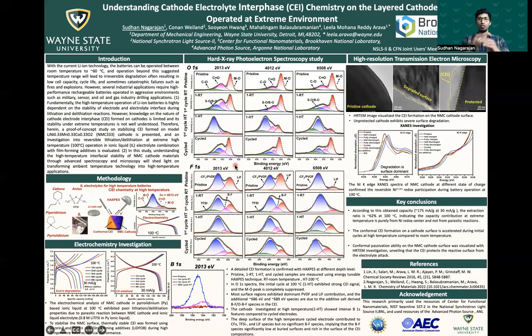So after that, we wanted to understand the surface of the NMC using hard X-ray photoelectron spectroscopy, using different photon energies. We use different photon energies to understand the cathode interface at different depth levels. The take-home message of the oxygen 1s spectra is that at high temperature during initial cycles, the cathode interface formation was accelerated. And from the fluorine 1s spectra, we clearly see that the boron-based surface species are emerging in the surface regions compared to deeper surfaces. So we supported that with the boron 1s spectrum, and as you can see, at high temperature during initial cycle, the boron signal is intense compared to other sample conditions.